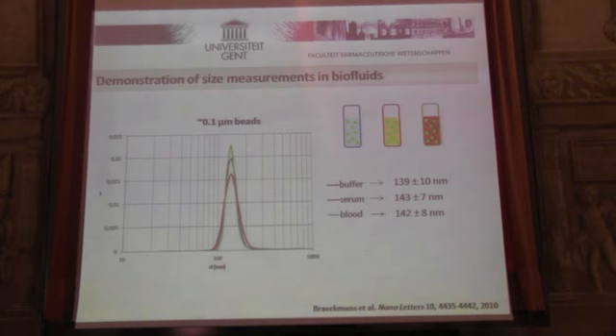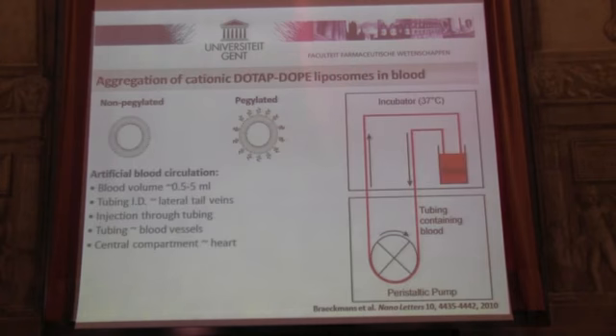To show that it works in biological fluids, we did this experiment. We took fluorescent nanoparticles, nominal size 0.1 micrometer. We measured them in buffer. The actual size was about 140. We also dispersed them in serum and in whole blood. We do the tracking, and as you can see, by taking into account the viscosity of the solutions, we can have these very accurate size distributions and average sizes.